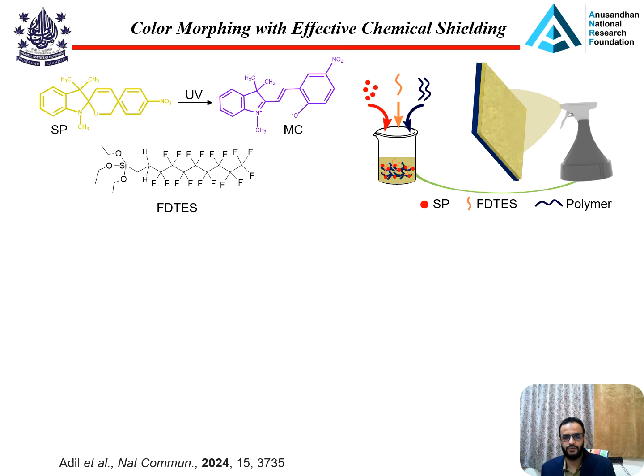However, these super hydrophobic surfaces are unable to repel low surface tension liquids. In order to repel them, another property is introduced, that is super oleophobic surfaces, which repel both water as well as other organic liquids or low surface tension liquids. So here we have designed multifunctional super omniphobic surfaces which repel both water and other low surface tension liquids,